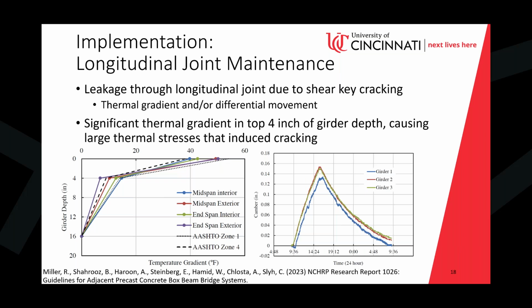These graphs are not our own, but from this NCHRP project, the report came out in 2023, where they were looking at this effect of thermal gradient and causing cracking of the shear keys. So the image on the left is showing, as you go down in the depth of the girder, the different thermal gradients that were observed just from day-to-day heating and cooling, the sun exposure to the girder. We're not talking about fire temperatures, we're talking about just day-to-day temperature fluctuations. So in the top 4 inches of the girder, you could see a fluctuation of 50 degrees that can occur.